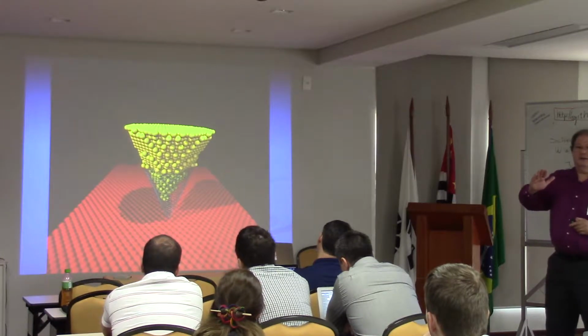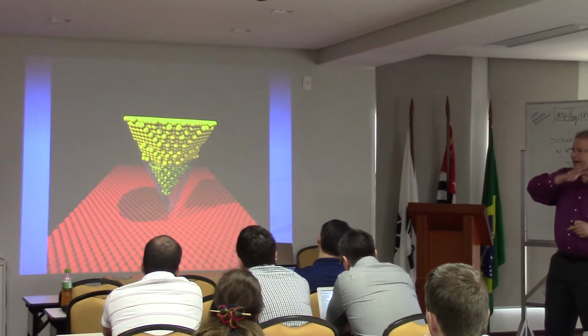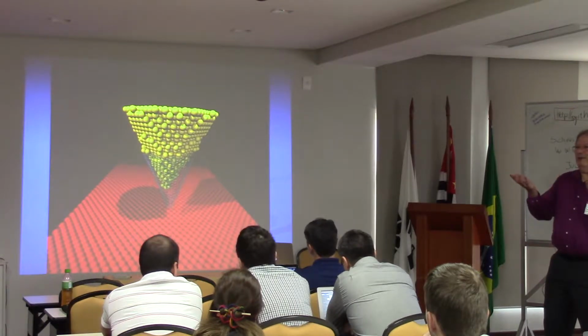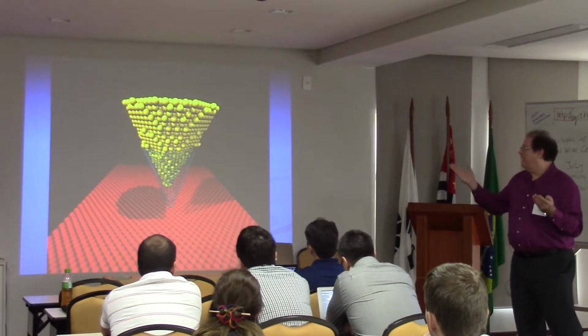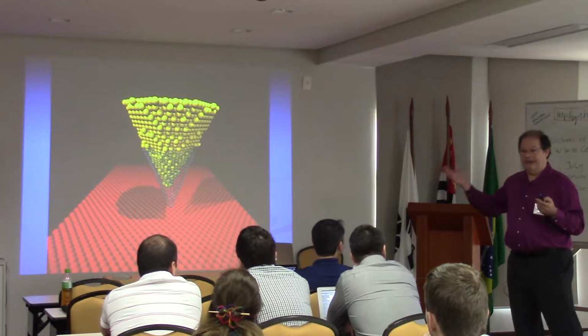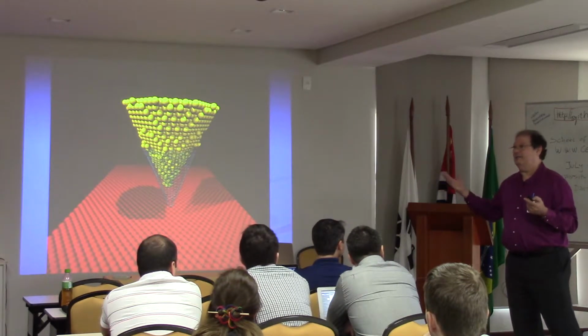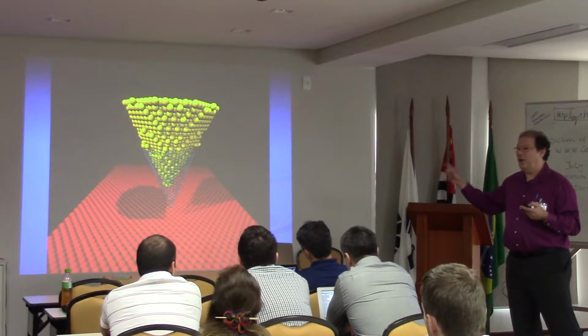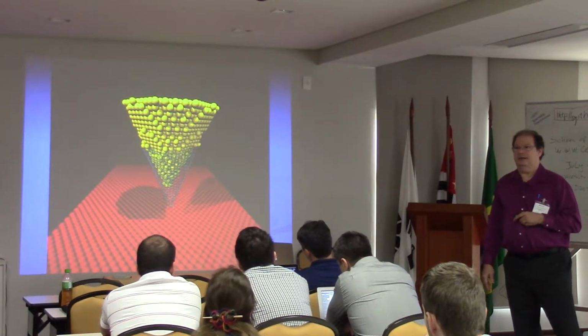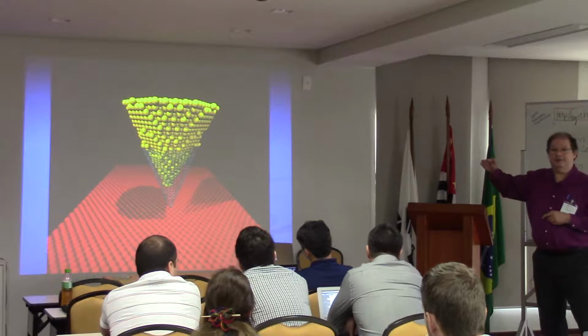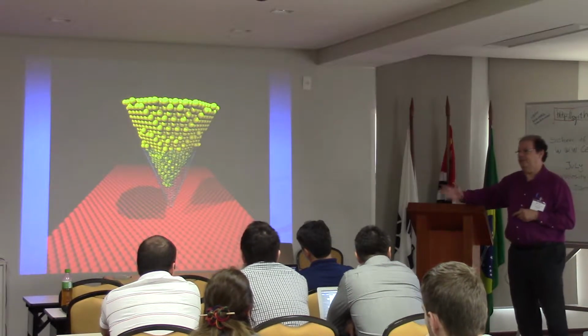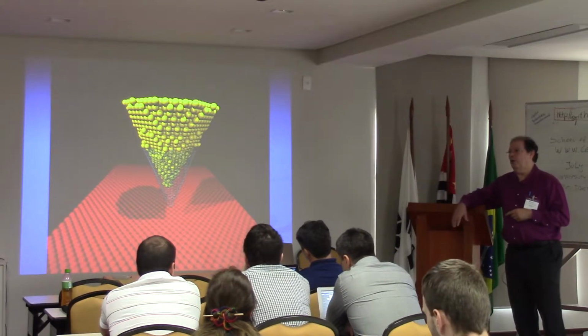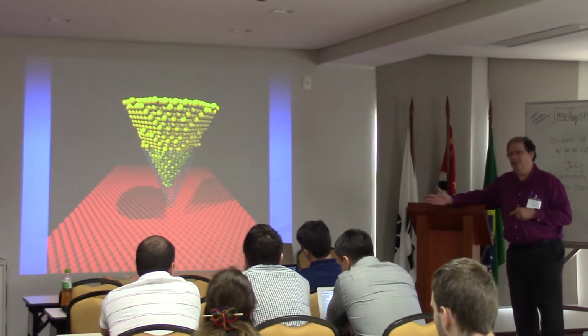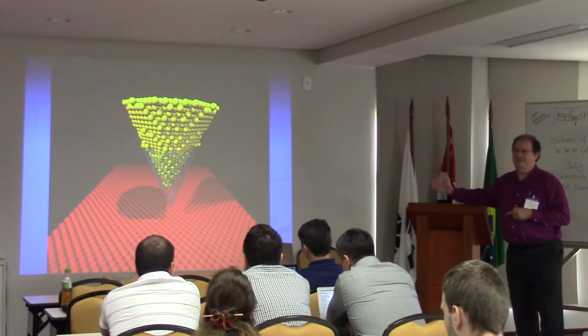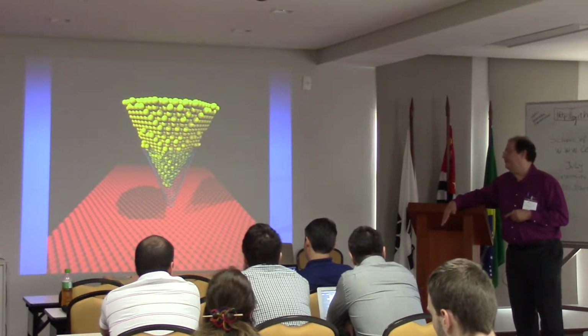It blocks the sliding of the metallic planes, because the topology of the cone fits the tip. So it's like gold starts to behave like platinum. It behaves like a harder metal. That's the secret why the tip becomes so much better. The blocking of the metallic plane sliding provides this phenomenon. Again, simulation not only helps to interpret the data, it found an interesting phenomenon that explains the experimental data.